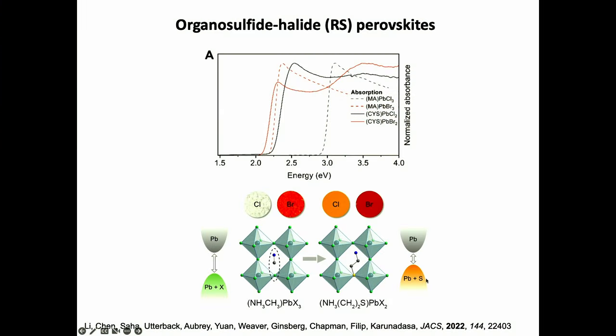Well, here I have a very simple band structure that explains it. In the halide perovskite, the filled states are mostly halide. But in the sulfur perovskites, even though there are halides in here, and more halides than sulfides, the sulfur states are at the top of the filled states. Meaning that as long as I have sulfur, I can get a small band gap, even in a chloride perovskite. Which is really nice news for us, because that means we can use the stability of the chloride perovskites and yet have the band gap of the heavier bromide or iodide perovskites.